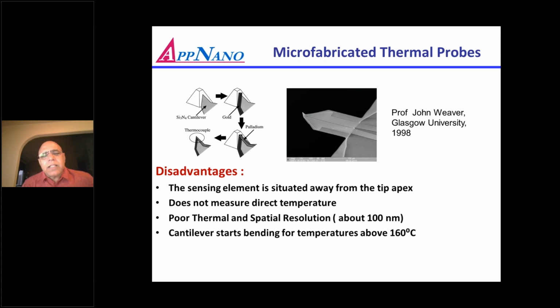The third drawback is that, as I said, this is a silicon nitride cantilever with metal, so there is a thermal expansion coefficient much different from the metal. When it goes to high temperature, anything above 160 degrees Celsius, it bends, and it bends beyond use. So you cannot use it beyond that. The poor thermal resolution and the limited temperature capabilities are the limitations of these probes.